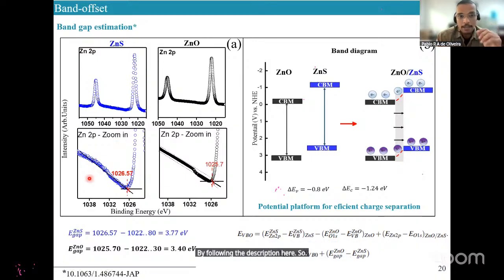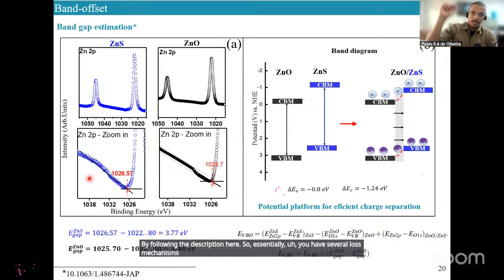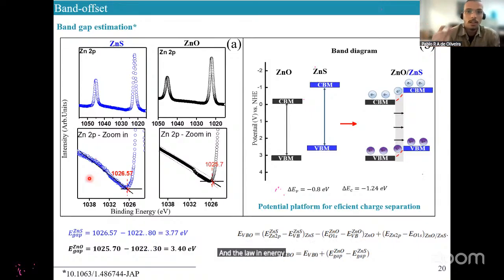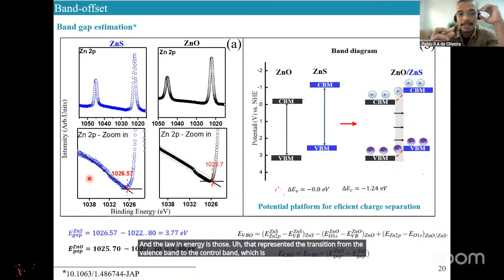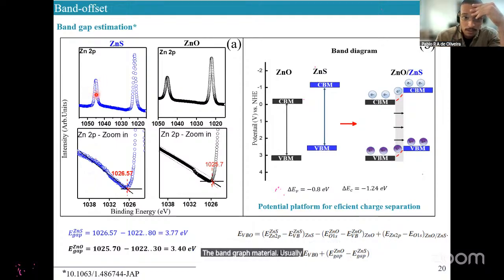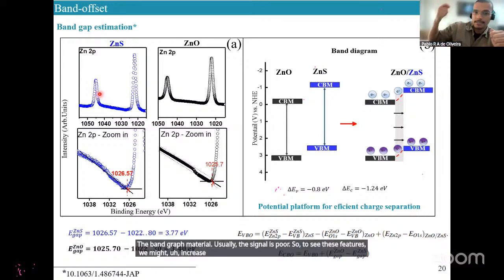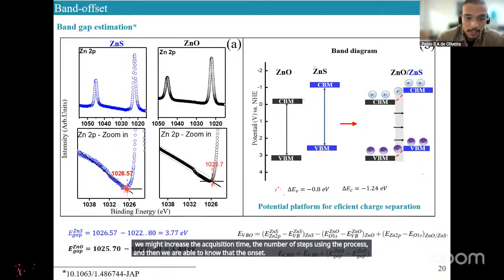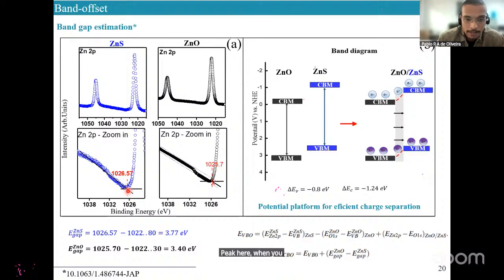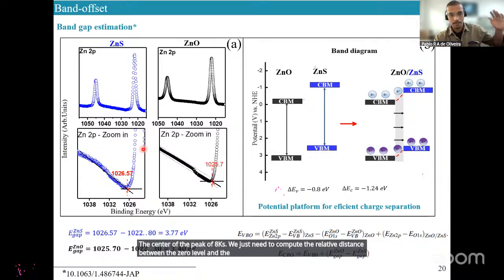Essentially, you have several loss mechanisms during the photoemission, and the lowest in energy are those that represent the transition from the valence band to the conduction band, which is exactly the band gap of the material. Usually the signal is poor, so to see these features we might increase the acquisition time and the number of steps, and then we are able to note the onset of the peak when you highlight the zero level and fix the center of the peak in each case. We just need to compute the relative distance between the zero level and the fixed center of the peak.